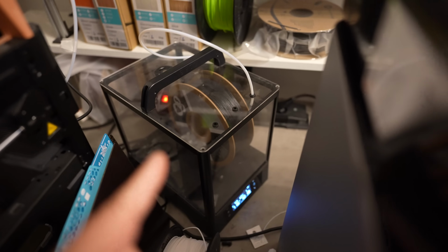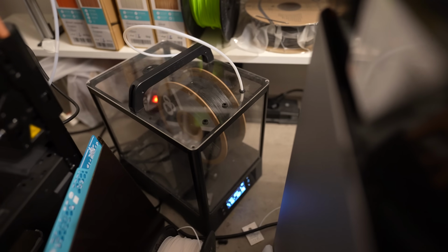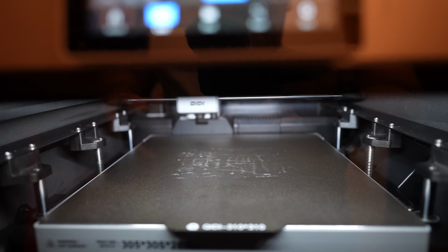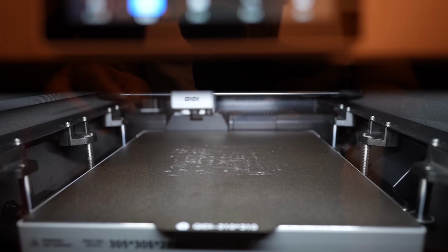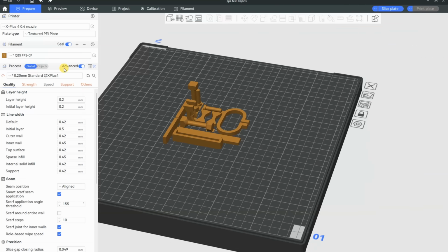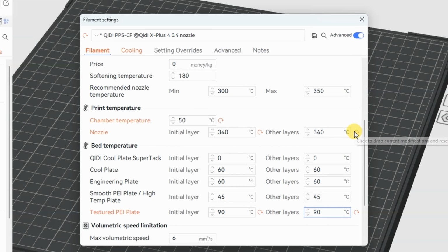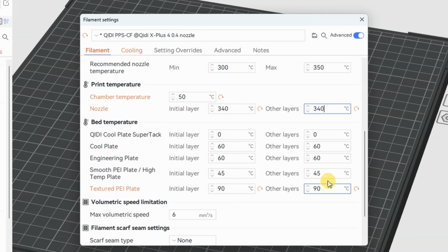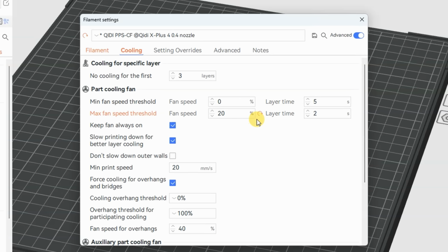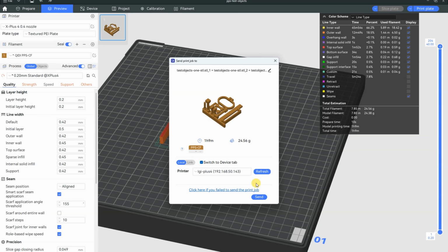Oops. I dried the filament a few hours at 70 degrees Celsius. Filament is loaded and the printing will be on textured PEI sheet with some glue on it. Settings in the slicer and profile for this material already exist, only I changed the temperature from 320 to 340 degrees Celsius. I tried to use my experience with the previous PPS material I tested on this channel. 6 will be the maximal flow rate, and the part cooling I reduced from the default 30 to 20%.